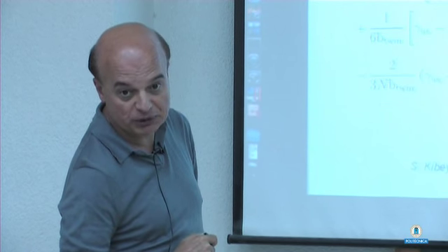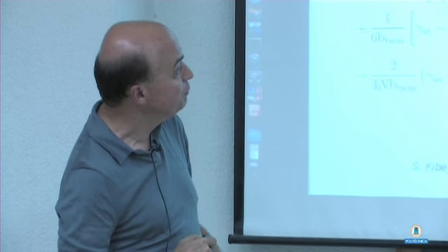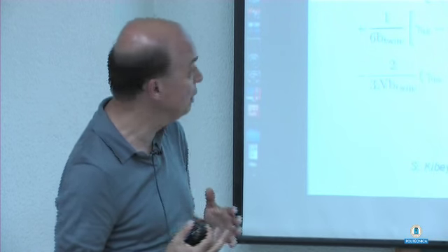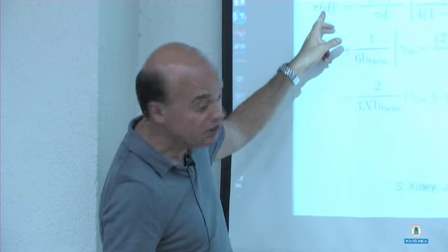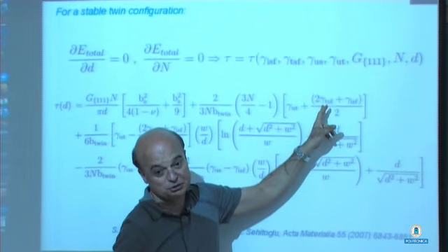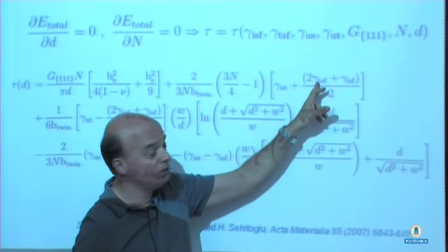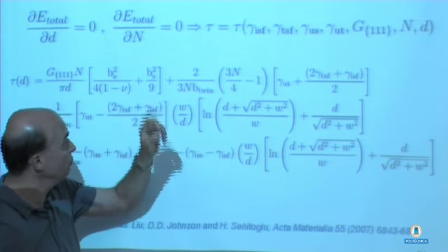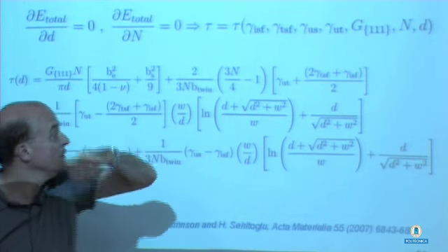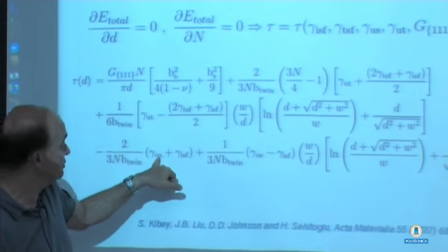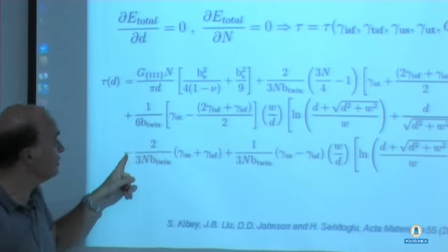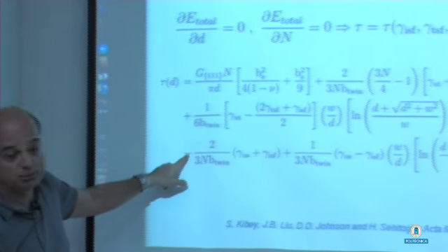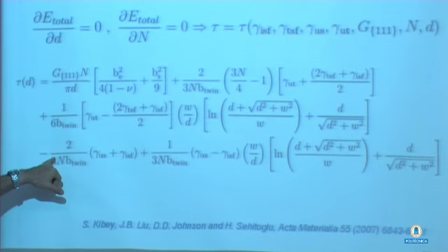For a stable twin configuration, we have to look for the minimum for this total energy expression. If you do that, you get this result, which looks a little complicated, but I'm going to simplify it. But the important thing is this is the twinning stress. It is a function of gamma ISF, but it is also a function of gamma TSF, that's the twinning stacking fault energy. But moreover, it's a function of gamma UT, the peak, and it's also a function of gamma US, which is appearing in here. Note the signs here, and this will come into play. These are the positive terms here, and there are some negative terms here.